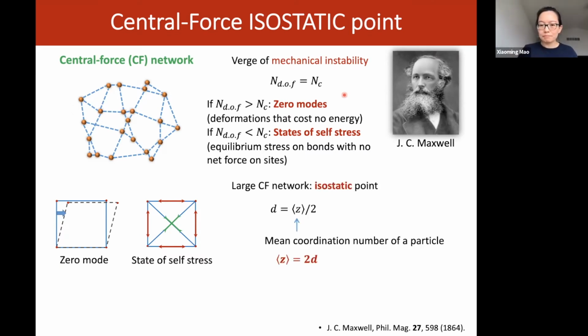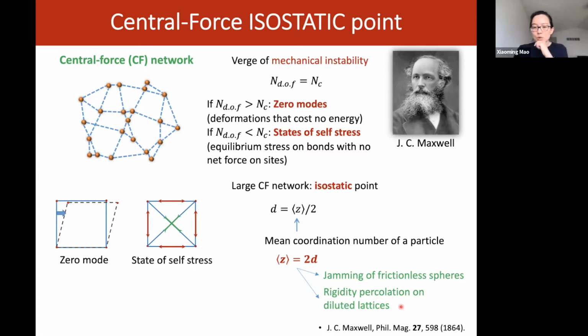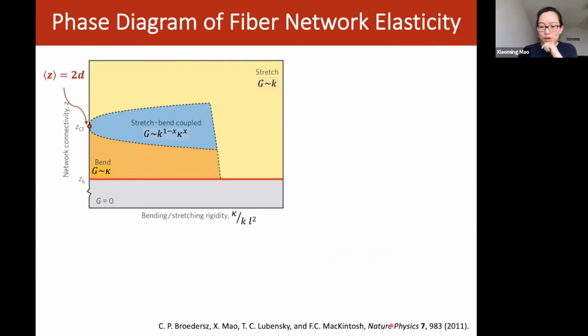Okay, so if you have a large central force network, you can write this equation as averaged quantities per particle, where the degrees of freedom is d, as a point-like particle in d dimensions. And the number of constraints is the coordination number divided by 2. The coordination number is just the number of arms stemming out from one site. Each arm, as a linear spring, gives you one constraint, but it's shared by the two neighbors, so it is divided by 2. This equation is often written in the form of z equals 2d, and is a pretty well-known equation in soft matter because it is the point where the jamming of frictionless spheres happens and where the rigidity percolation occurs on diluted lattices.